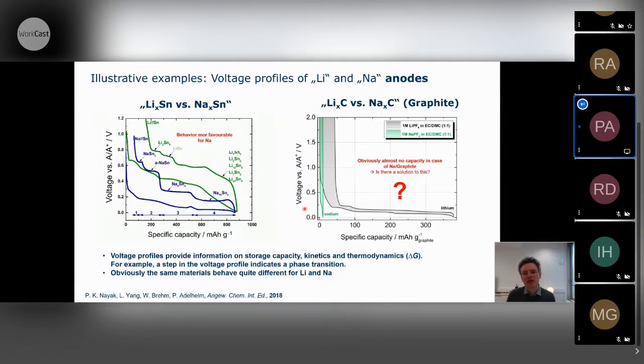On the right-hand side, you see a comparison of graphite. And graphite is a very interesting example because almost all lithium-ion batteries use graphite as anode material, because lithium forms this nice LiC6 intercalation compound, and this is shown here. So lithium goes into the graphite and lithium goes out. This all happens at around 0.1, 0.2 volts, so very nicely suited to reach a high energy battery. Unfortunately, for sodium, the capacity is 0. It works for potassium and for other alkali ions, but not for sodium. So what we were wondering is whether you can still use sodium ions and graphite in sodium-ion batteries. So we came up with another approach that I will discuss on the following slide.